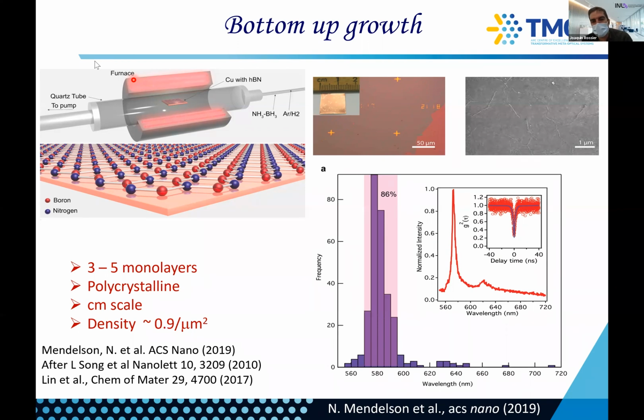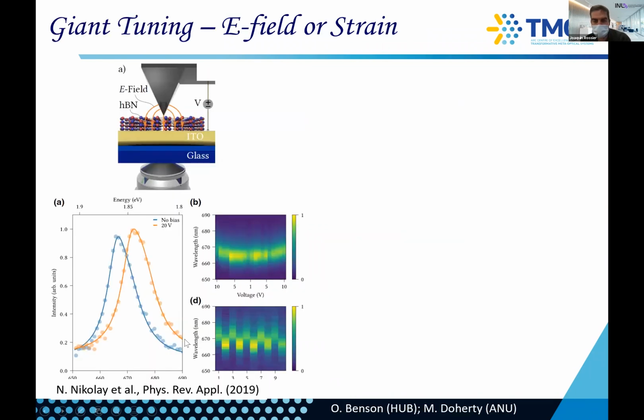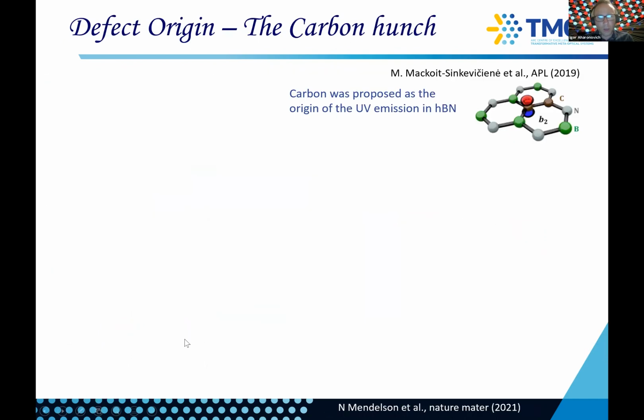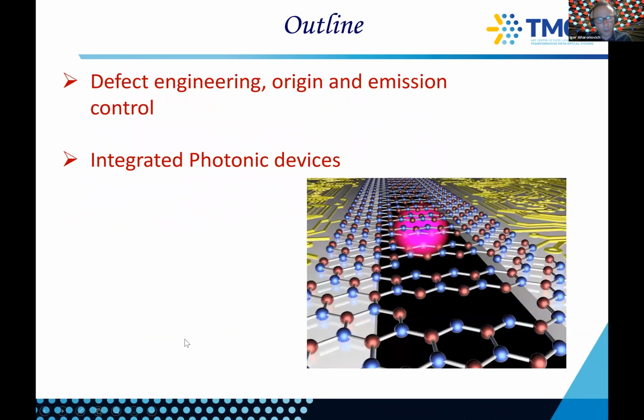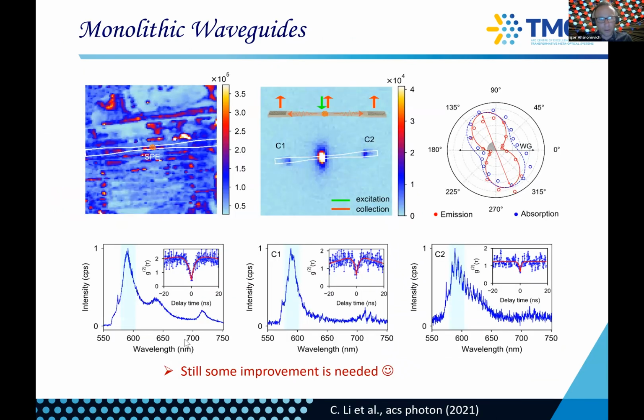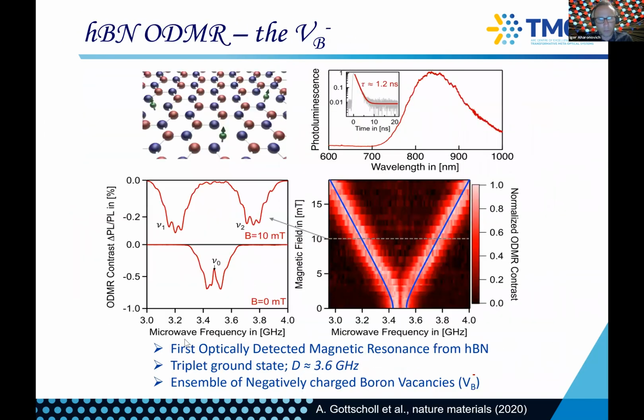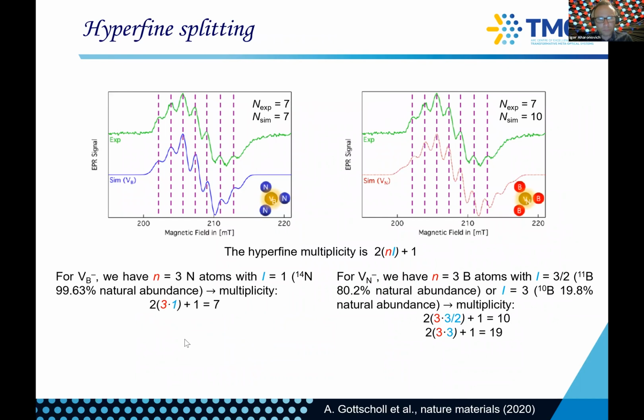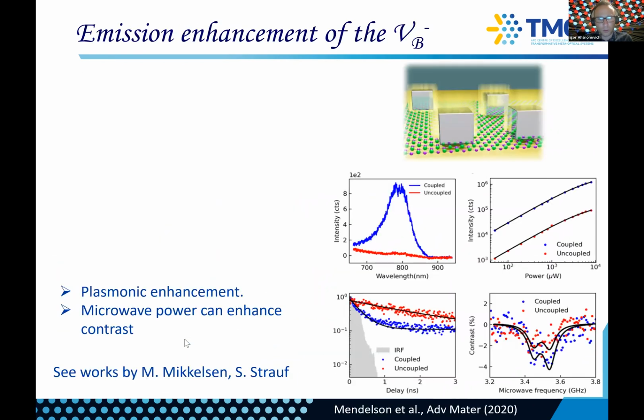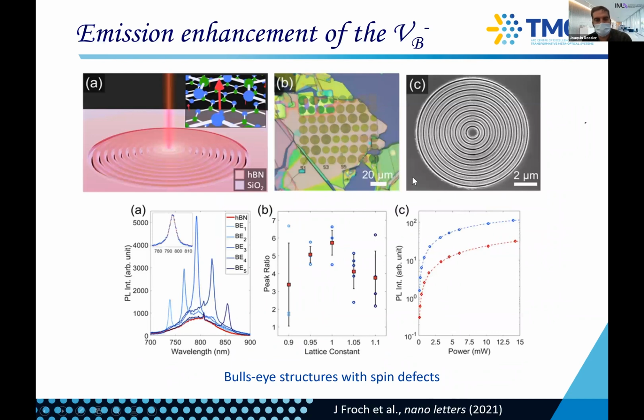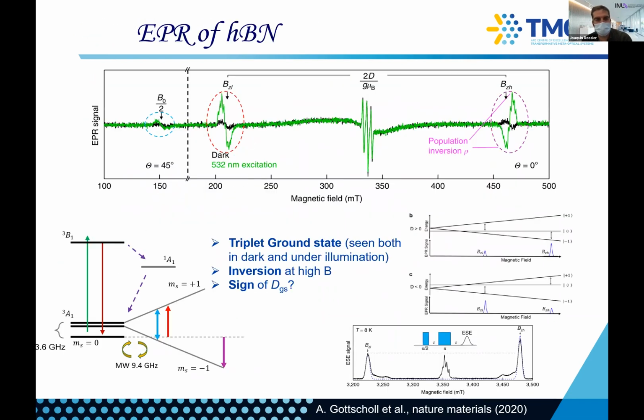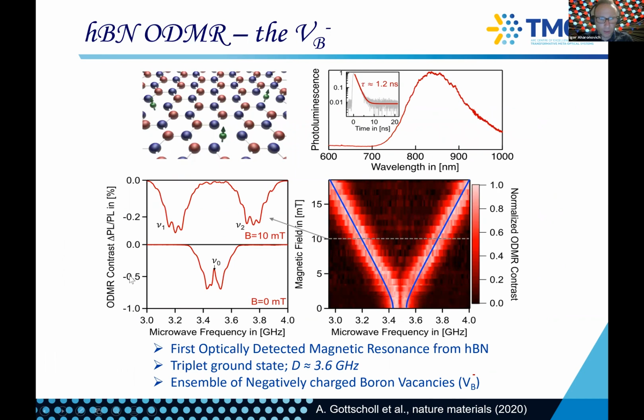But the boron vacancy, you said this is not so emissive, right? So from the side of applications, it's not so interesting, or did I get that wrong? No, you got it right. So it's not that bright, but it has ODMR, which is the spin properties. So in this regard, it's even more interesting, because I'm just scrolling through. Yeah, because you can see ODMR. So this is a bad ODMR. Let me find a good ODMR. Yeah, so you can see very nice spin dependence, and you know the defect. So okay, thanks a lot.